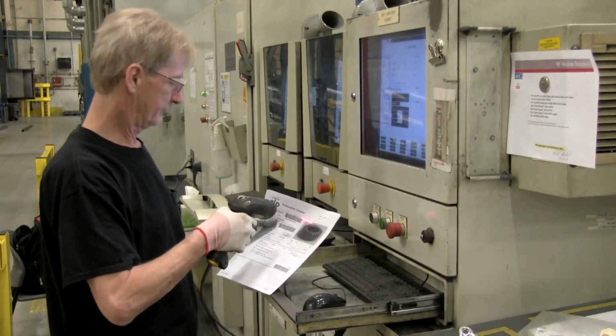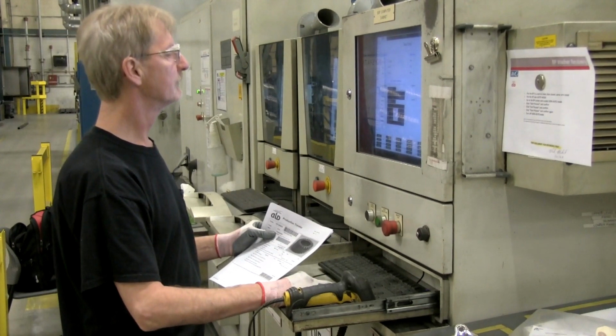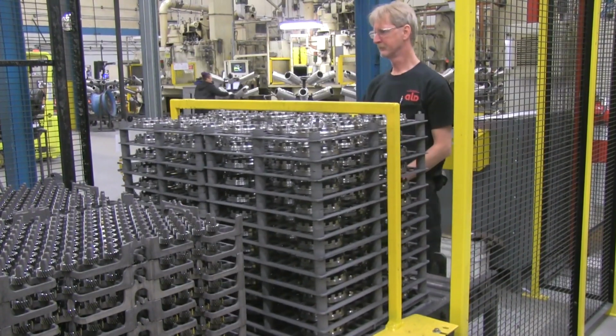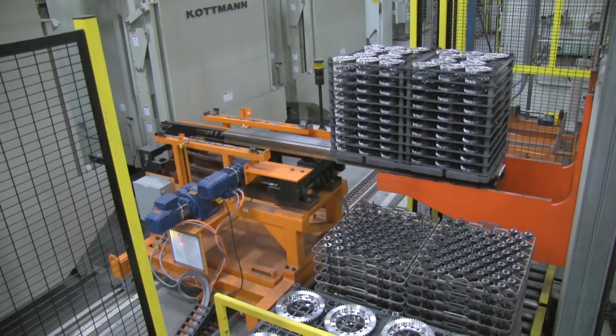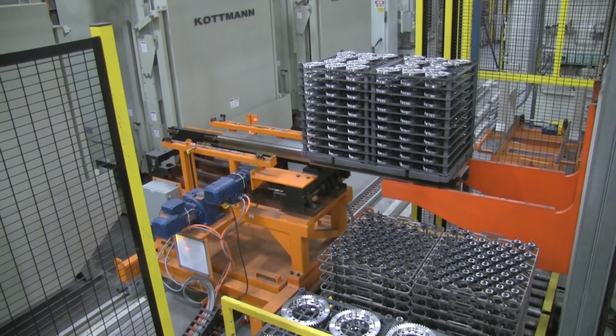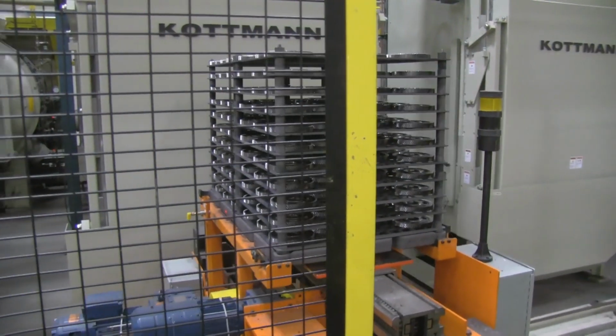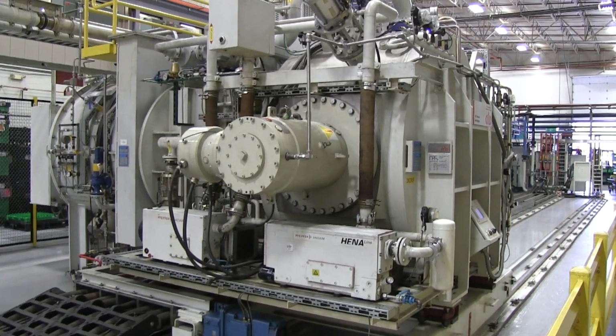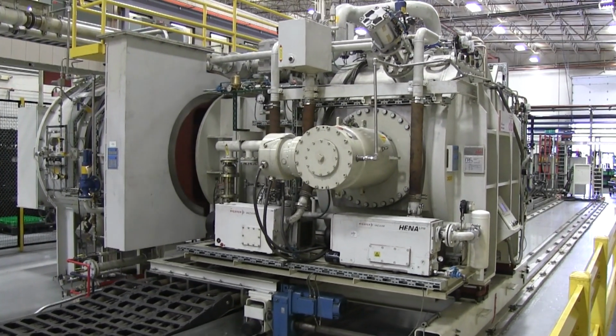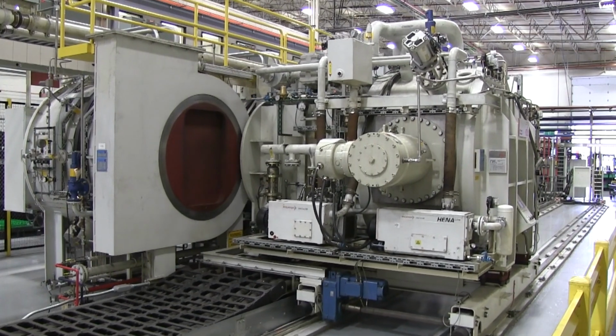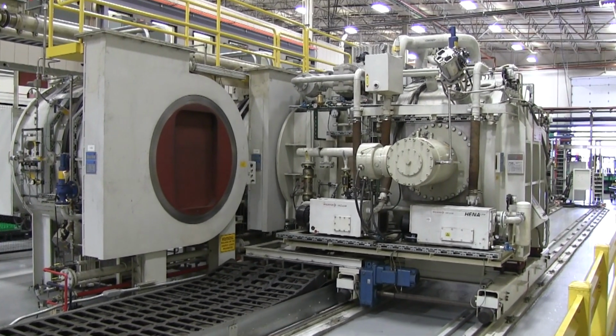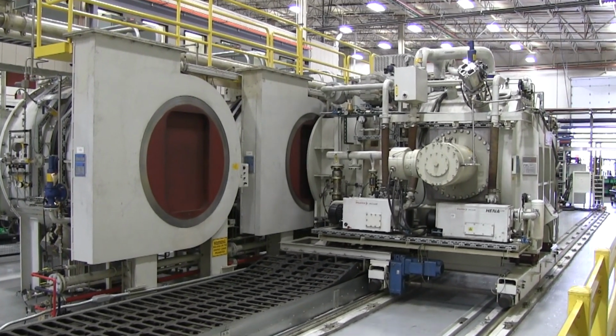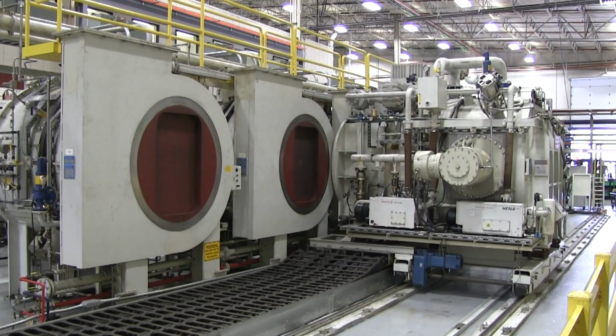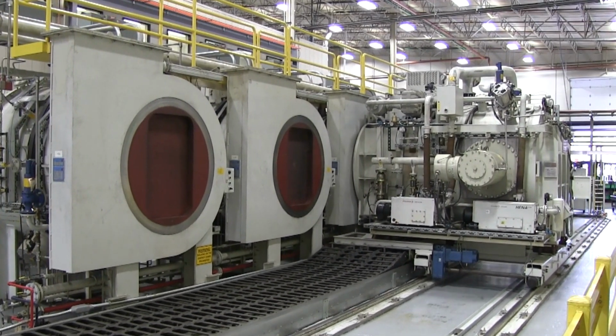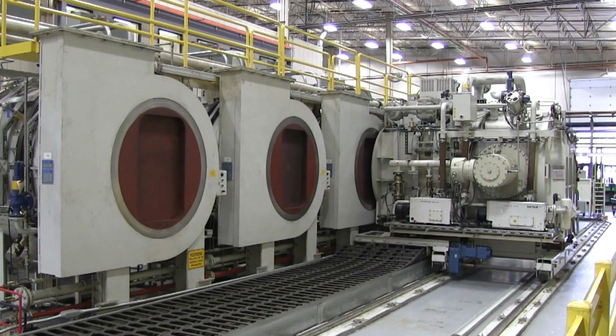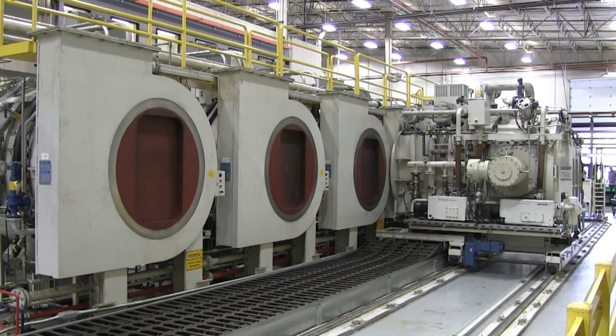Based on a sequence schedule, an operator scans the traveler for the load and transfers a load from the cart to the load conveyor. The scan includes the process recipe for that part, which includes all steps needed to automatically heat treat that load. Our ALD manufactured ModulTherm heat treat system is a technological marvel. It connects up to 12 independent vacuum treatment chambers with a transfer, an external quench chamber that moves on a rail system. The equipment is extremely flexible because it allows many different processes to be active at the same time, all of them using a common quench system.